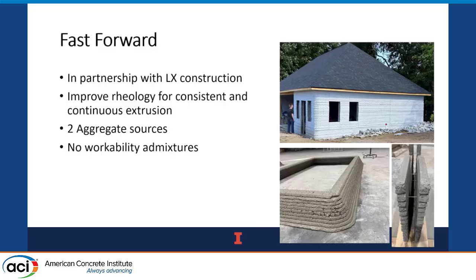So they wanted it to look nice, but they also wanted these taller layer heights so that printing time can be cut down. Their goal would be to print something like this in about a week. This was about a 2,000 square foot garage where the printer they have is a Cobod, so it's a gantry style, sits on the perimeter, and they would be able to basically print continuously. And with this structure, I think it was about a 20-minute layer time.